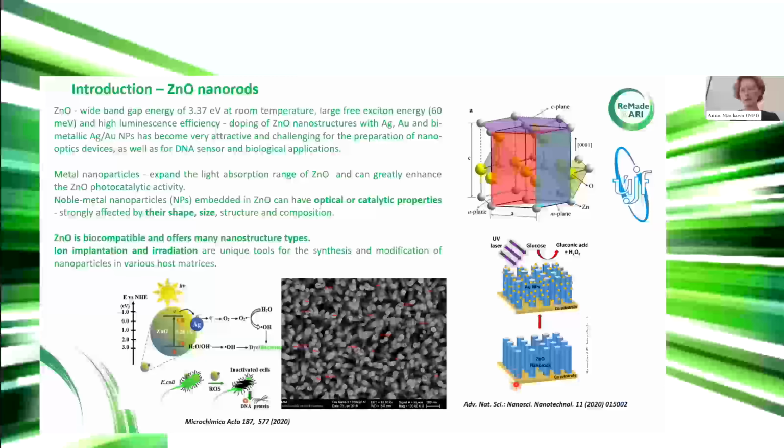So we have a zinc oxide nanopillar. Zinc oxide is a semiconductor. So if we irradiate zinc oxide with UV light, then we have creation of electrons and holes. And if some harmful molecules adsorb on the surface, then due to reduction and oxidation processes they can be decomposed, which is great. So it means we can degrade a harmful biological or chemical molecule. And these nanostructures have a very high effective surface, so they are very suitable for this kind of